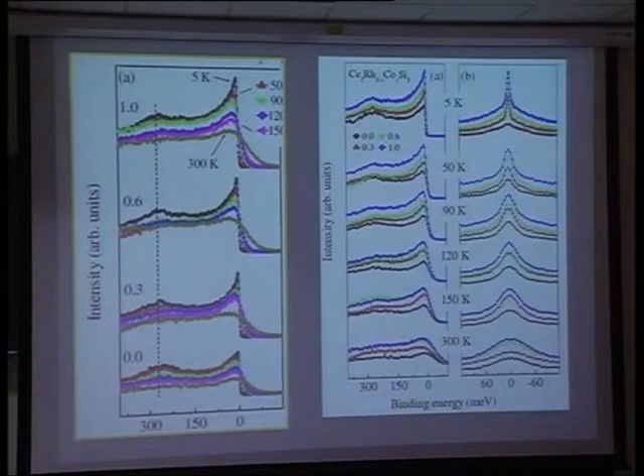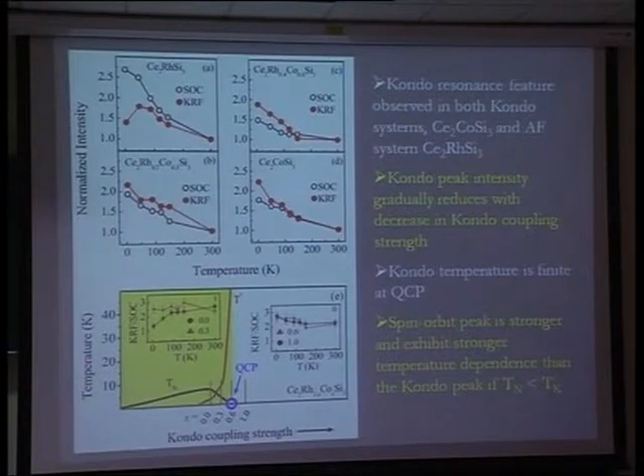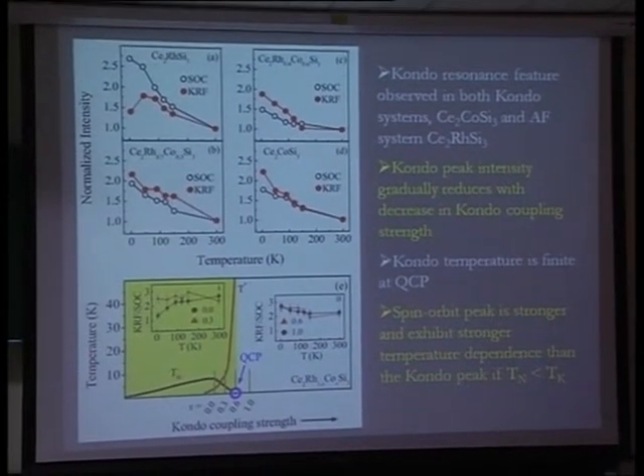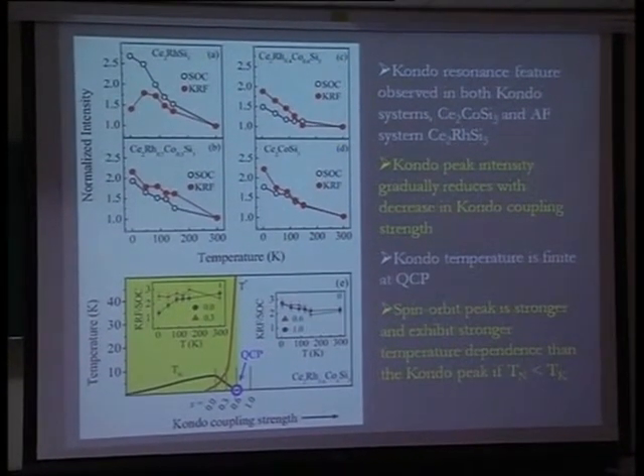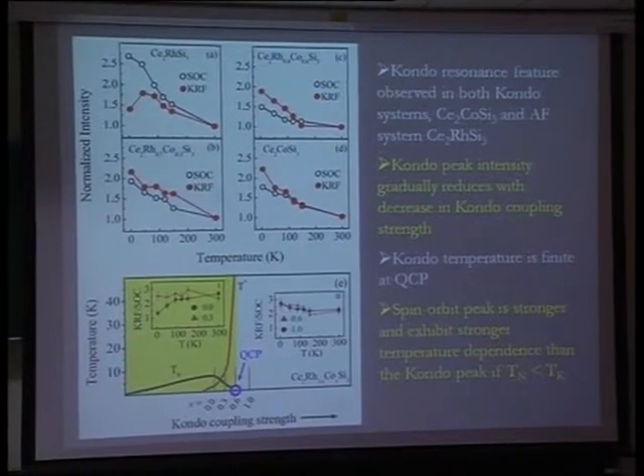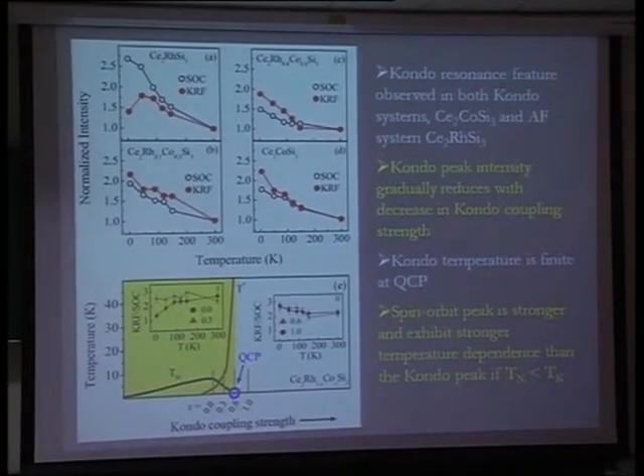So we can try to find out how this intensity can be evaluated. Here, at the same temperature, we have plotted the same peaks for different compositions, and this is the symmetrized data to find the Kondo resonance peak intensity at the Fermi level. Okay. So now we plot the intensity of the Kondo resonance feature, which is red, and the spin-orbit coupled peak, which is the empty black circles. You see that as you reduce temperature, all of them increase in intensity. Only the temperature dependence is very different.